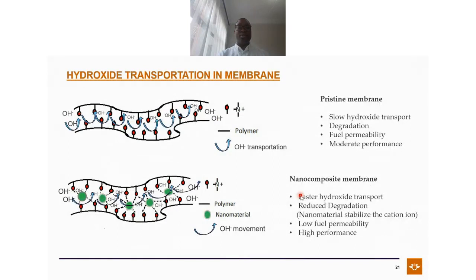This is the two comparison systems that we have. This is the system which does not have nanomaterial, and the system which has nanomaterial. As you can see, this material passes OH minus in what we call the hopping method. So it keeps on jumping until it comes to the side. But the moment we have the one with nanomaterial, the green one, the membrane is able to fast track the transportation of OH. Why? As you can see, the nanomaterial is able to align the transportation pathway. So basically, it creates a clear path for OH to move, which is why it takes less time. And this aids lower permeability of the membrane, and also high performance.